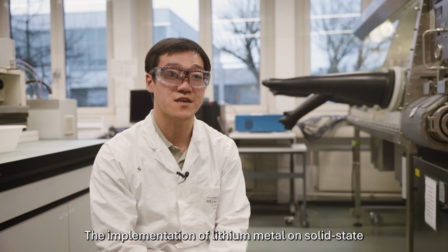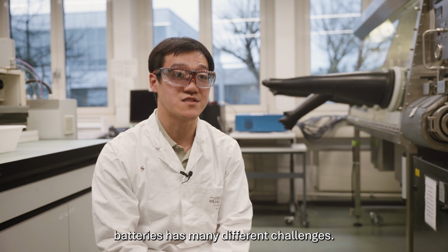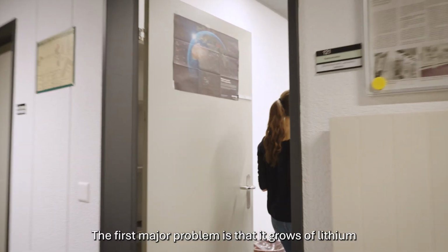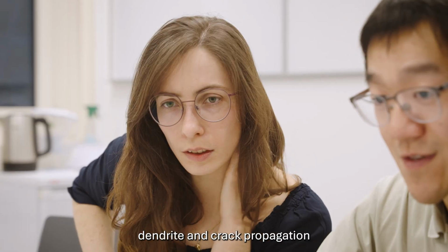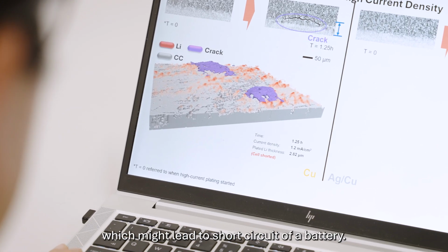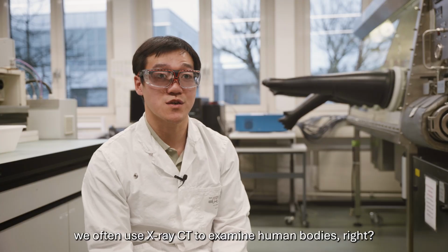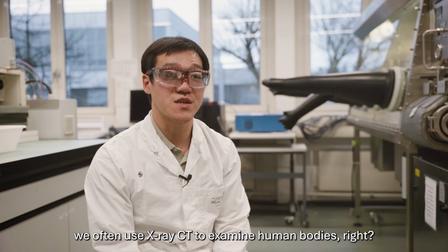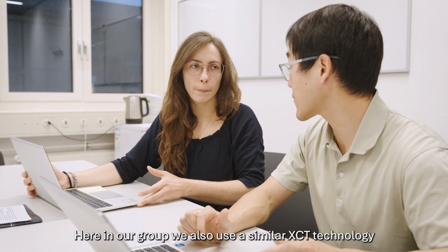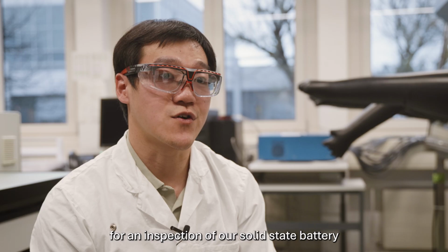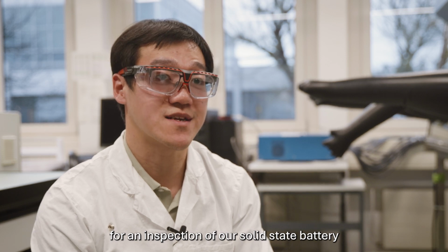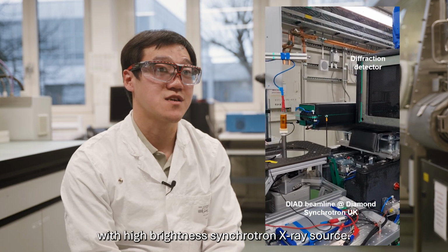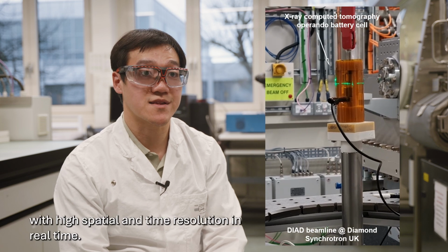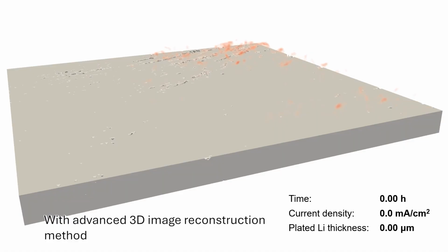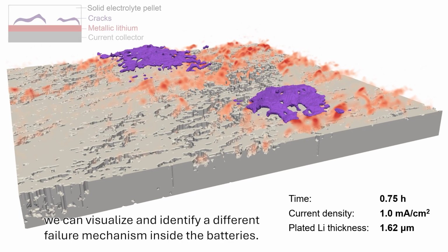The implementation of lithium metal in solid-state batteries has many different challenges. The first major problem is the growth of lithium dendrites and crack propagation, which might lead to a short circuit of a battery, and that can be fatal for the battery. In hospitals, we often use X-ray CT to examine human bodies, right? Here, in our group, we also use similar XCT technology for inspection of our solid-state battery. With a high-brightness synchrotron X-ray source, we can scan our battery with high spatial and time resolution in real time. With advanced 3D image reconstruction methods, we can visualize and identify different failure mechanisms inside batteries.